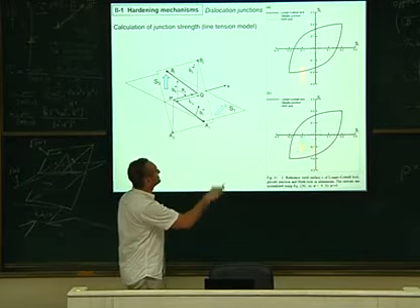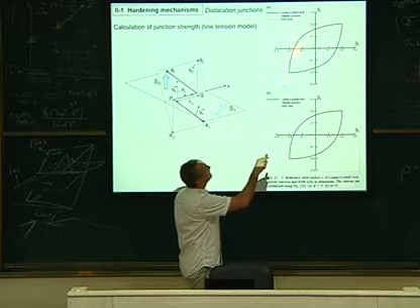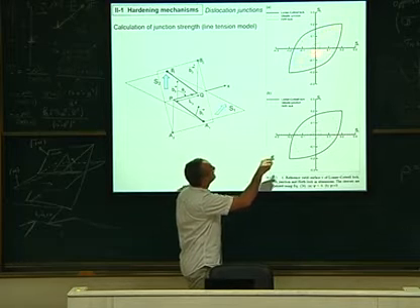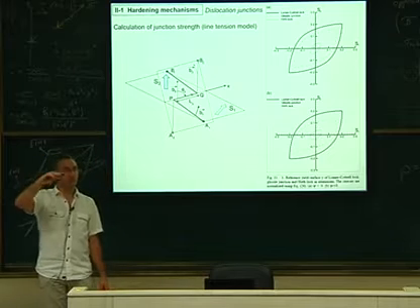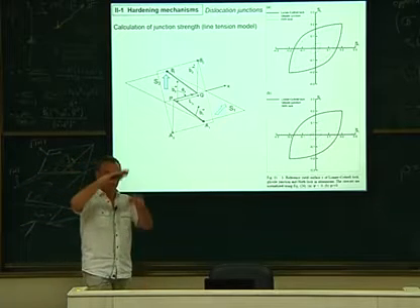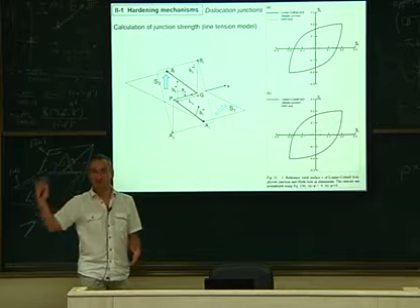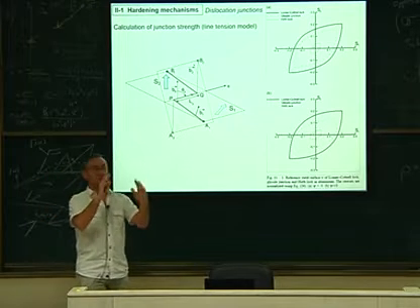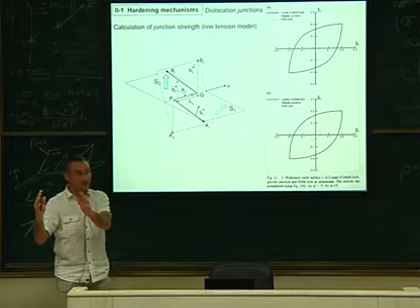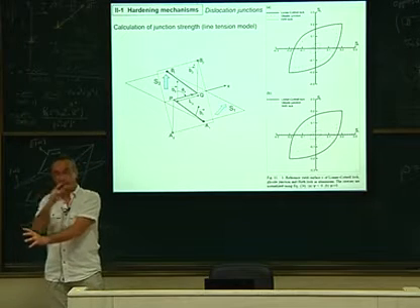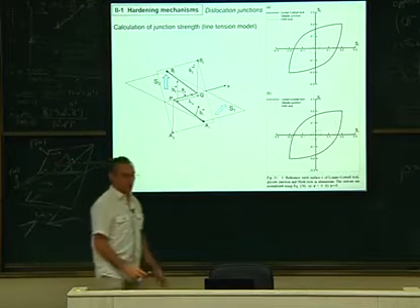So it's negative or positive. You don't have the same shape, but again the ranking is the same. Lomer is higher, glissile, and then Hirth. Okay. So you see that now we can rank the slip system interactions. You have a matrix, and within the matrix you have several parameters where you can specify the collinear, the Lomer-Cottrell, the glissile, and then the Hirth. And this is from the biggest to the weakest junction.